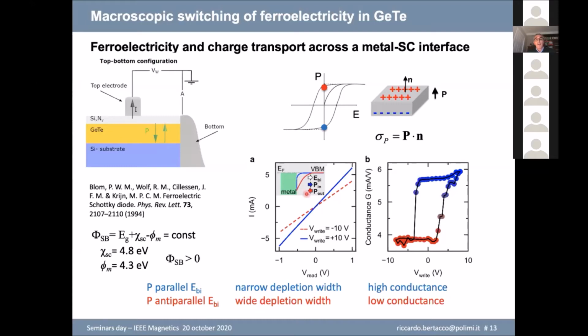While for the polarization pointing in the opposite direction, we have a wider depletion width, which means a low conductance. But the beauty of the story is that you can now follow the ferroelectric states just by looking at the conductance of your gating electrode. And this is shown here. This is a hysteresis loop of the conductance after application of pulses from minus 10 to about plus 10 volts. And you see that you have a hysteresis which is connected to the ferroelectric state.